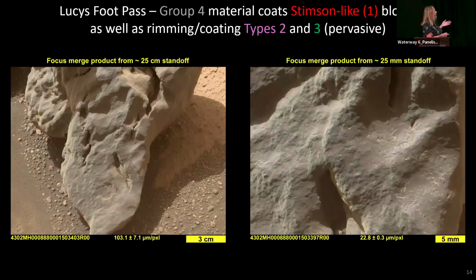And then finally, Lucy's Foot Pass is a really nice example, especially if you look at this close-up Mahli image on the right-hand side here. And you can see this coarser gray material and this smoother, kind of purplish material. And the composition of this block and those textures are consistent with a type 1 Stimson-Bradbury-like material with a coating of the type 4 gray material. So that type 4 coating and rimming material occurs on types 1, 2, and 3. And it's pervasive throughout the deposit.